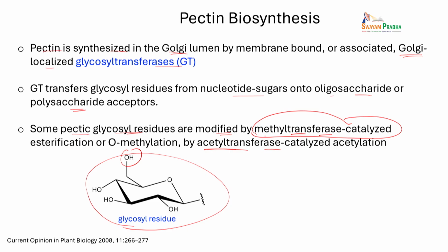So one way to look at this is, can you come up with programmed enzyme combinations that will take sugar and convert it into oligomers and polymers in controlled conditions, so that you can precisely control the type of sugar. If you want to build only homogalacturonan, you can do that, or if you want to change the degree of esterification, you can change the amount of the methyl transferase. If you want to acetylate the polymer, you can also control the amount of acetyl transferase reactions. Okay, so this seems to be one area, again with a lot of possibilities awaiting.